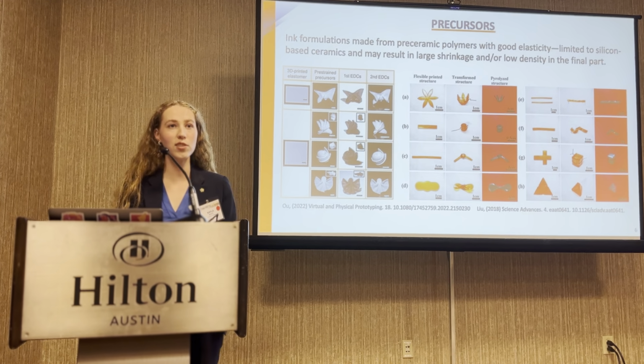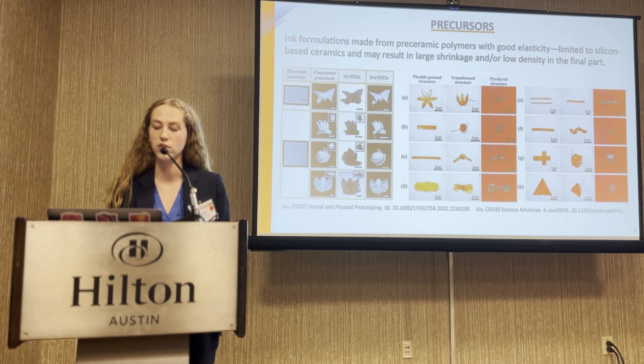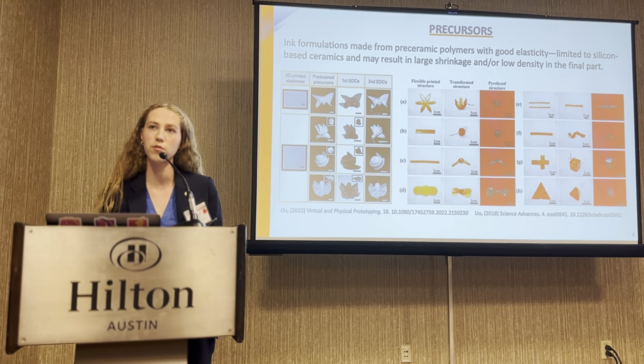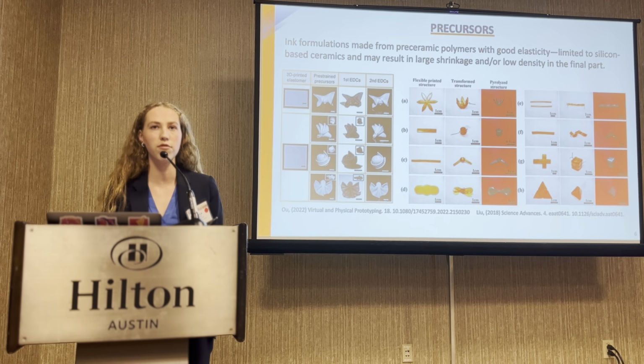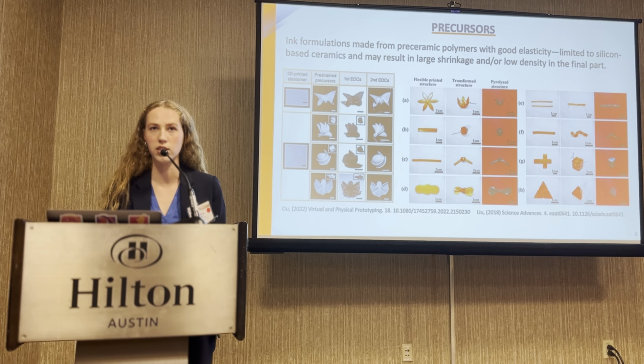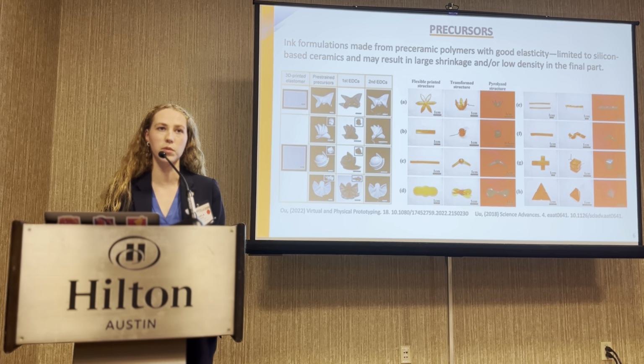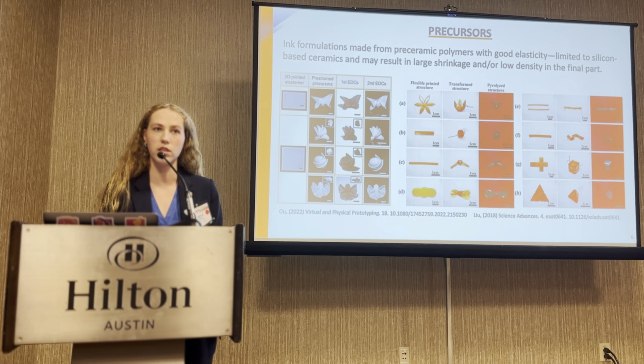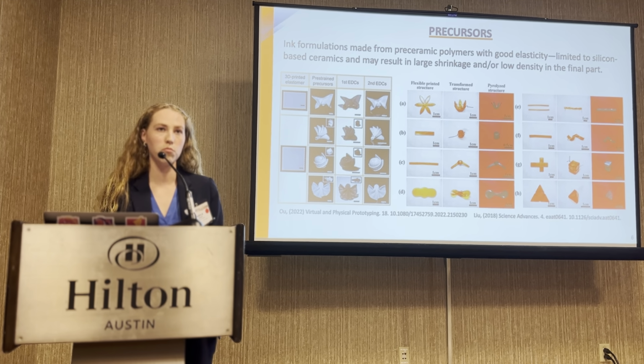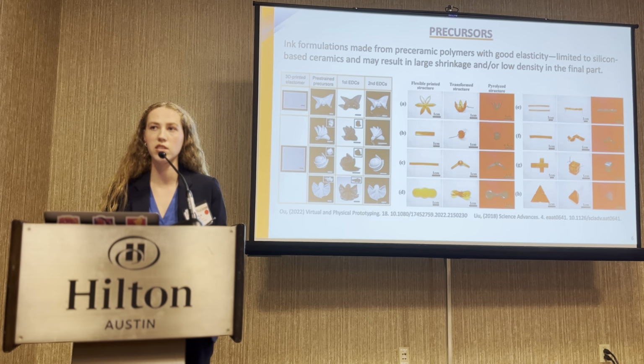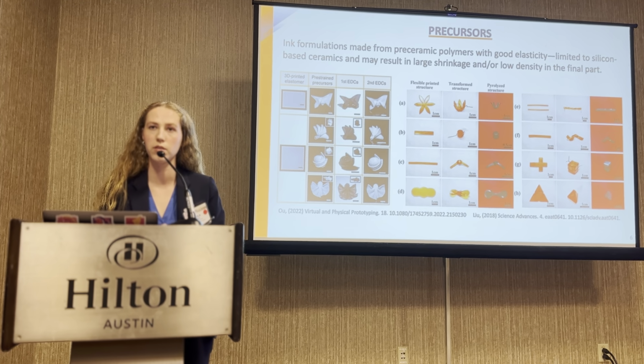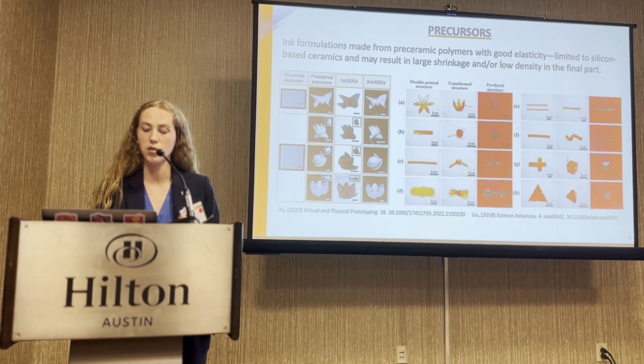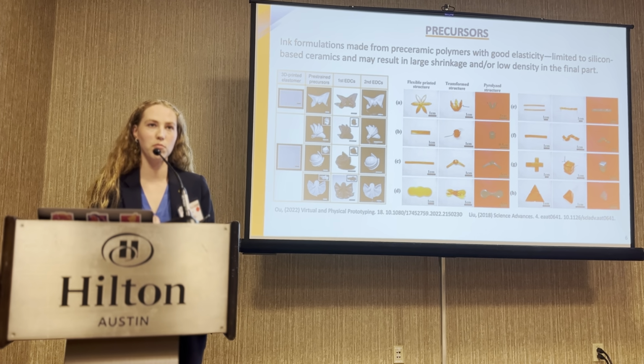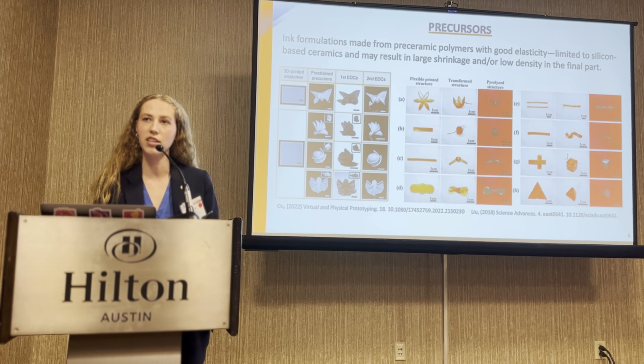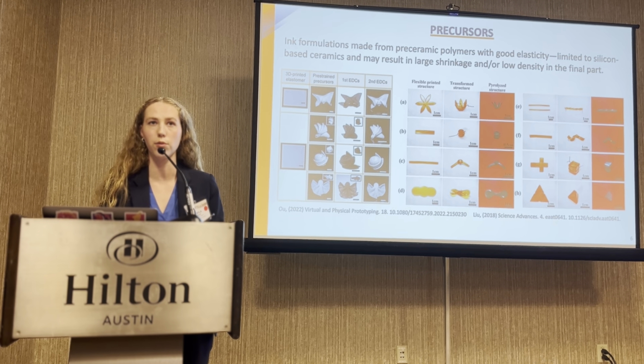And the expansion of this into the field of ceramic parts generally focused on polymer-derived ceramics, which need fillers to reduce the cracks and increase the density, and they're also very limited in the material scope. They're generally only silicon-based components. They also use a pyrolysis process that generally downgrades their mechanical performance. So here on the right, you can also see that the PDC that they used is limited in its shape memory and needed a wire in order to support it during the sintering process.